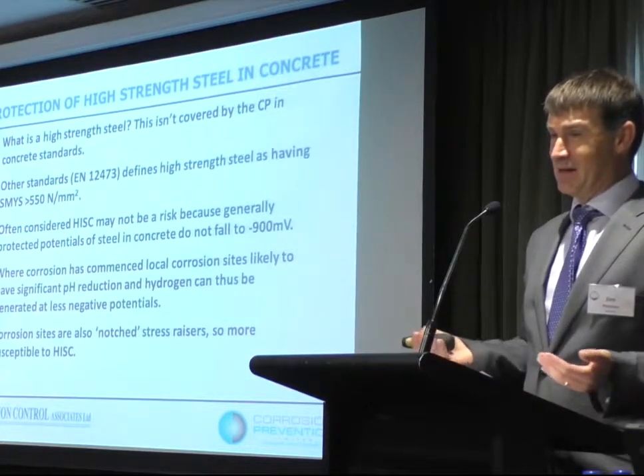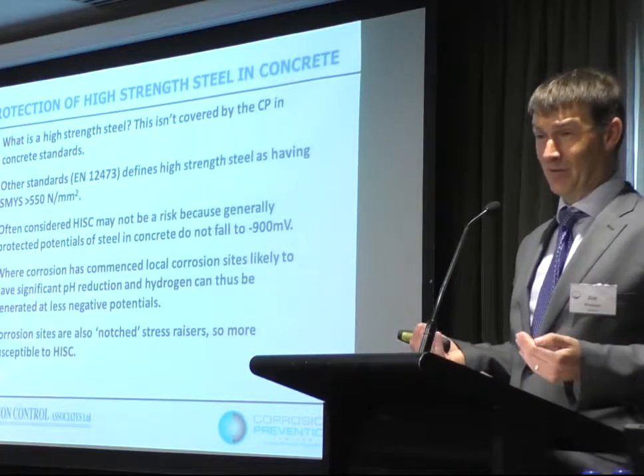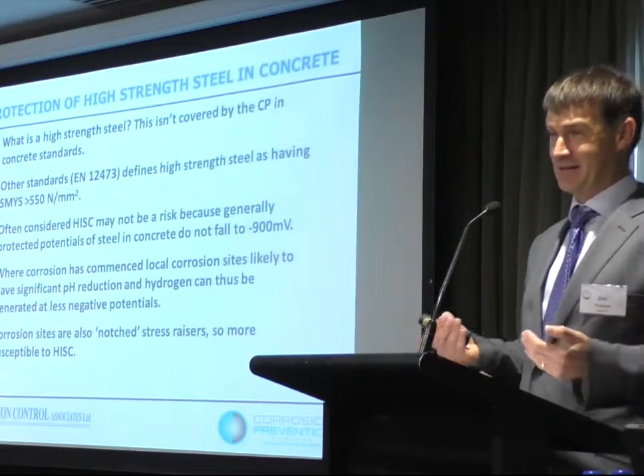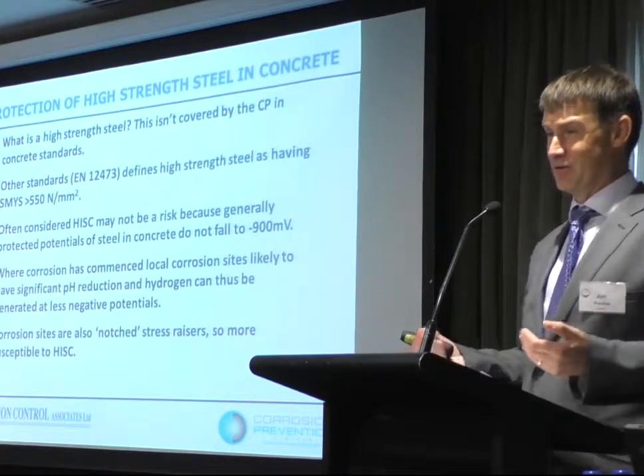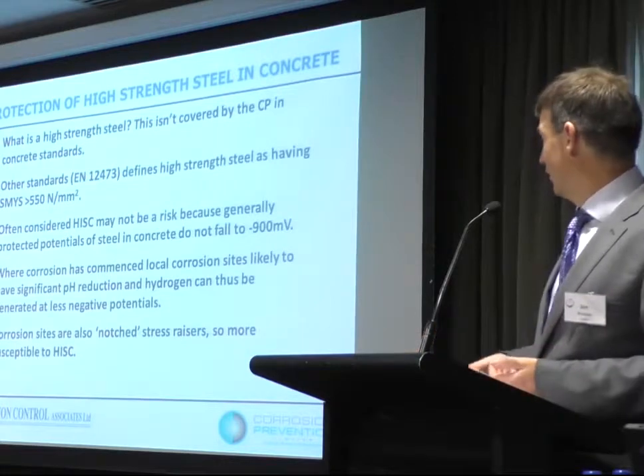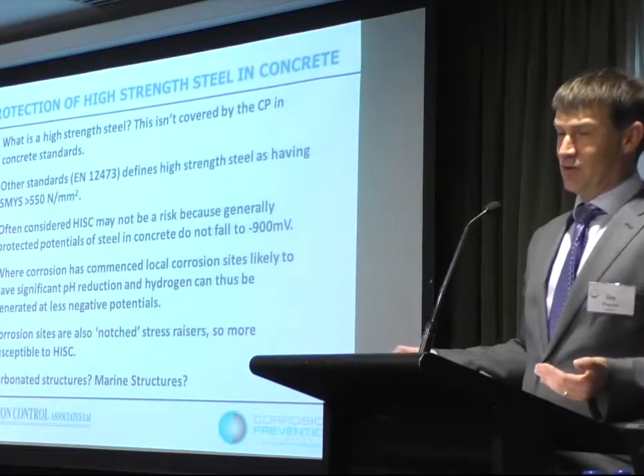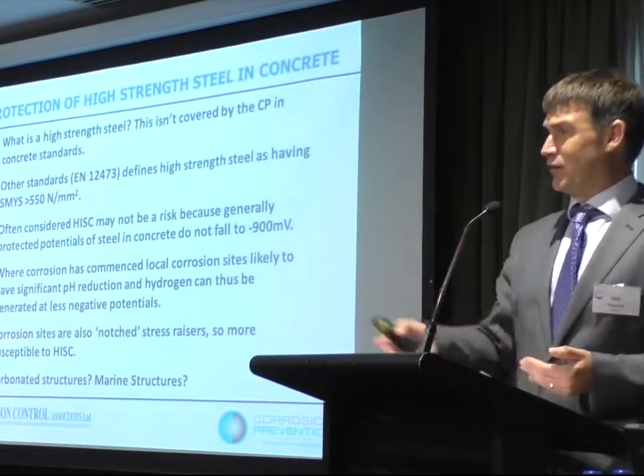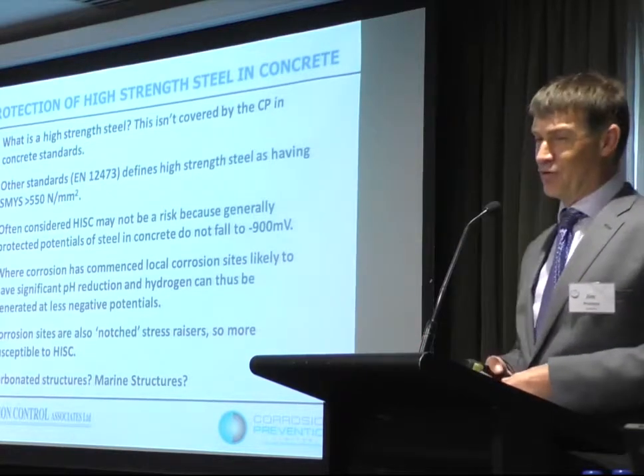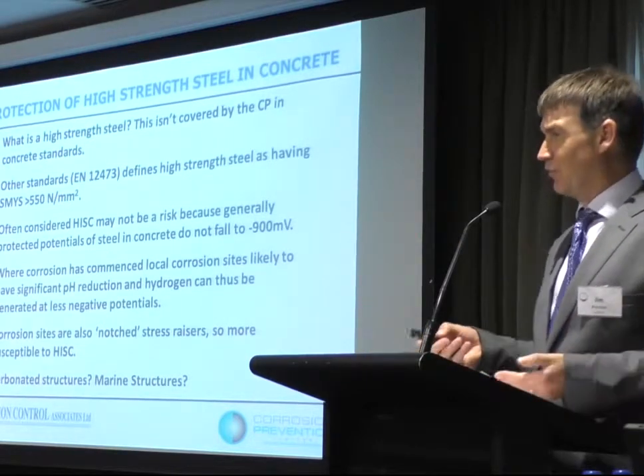If corrosion has taken place, have we actually got a higher stress in our bar than we would otherwise have, in which case are we making it more susceptible to cracking if hydrogen evolves? What about carbonated structures? What about our marine structure where we've got a crack that goes through the cover concrete to our bar? What's the pH in that environment?